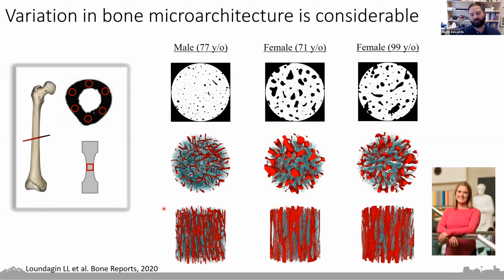We're not illustrating the bone here, but in fact, we're rendering all of the negative space inside of the cortical bone to illustrate the intracortical microarchitecture. The red is the intracortical vascular network, what we call Haversian and Volkmann's canals. People tend to forget that about 5 to 10% of your cardiac output goes to your bones. So there's a pretty interesting looking vascular network that varies considerably between people, sex, ages, disease states, physical activity states. These little dots here in blue, I hope you can see them, are in fact where the osteocyte lacuna lives. That's another source of porosity that we see in bone.